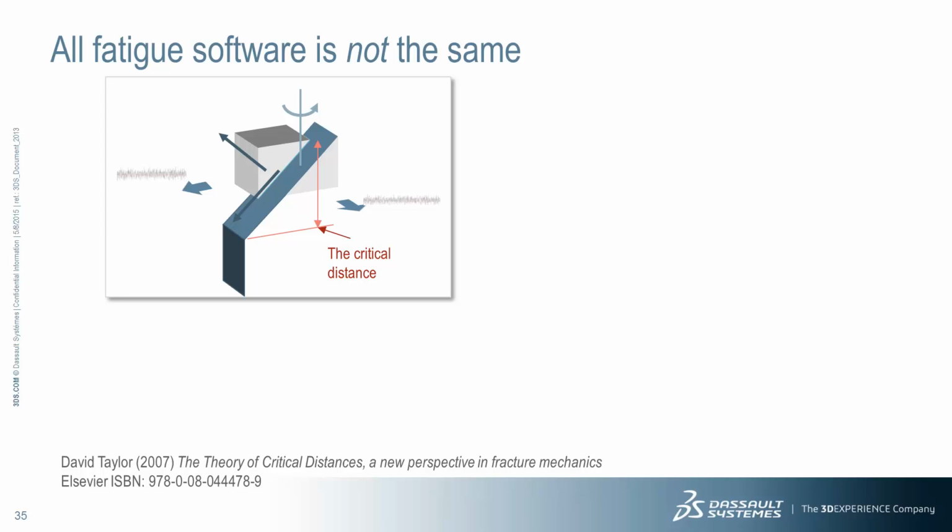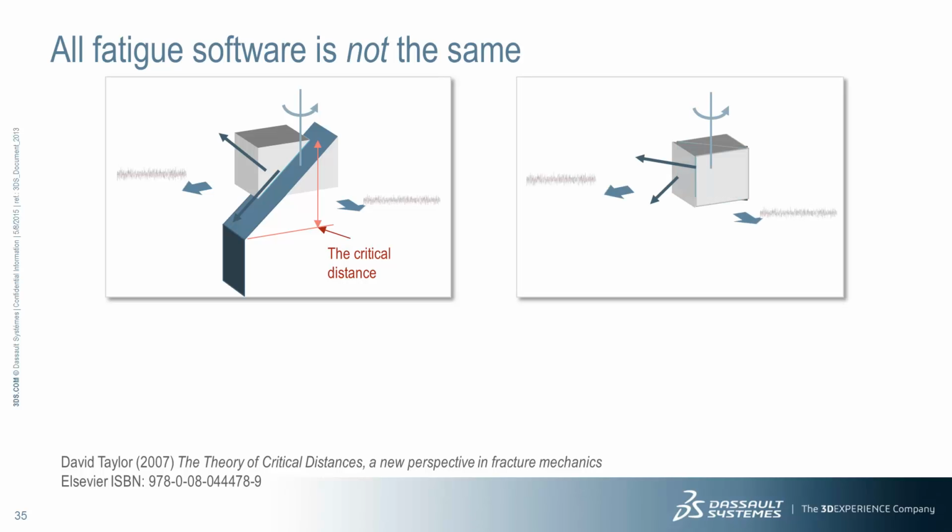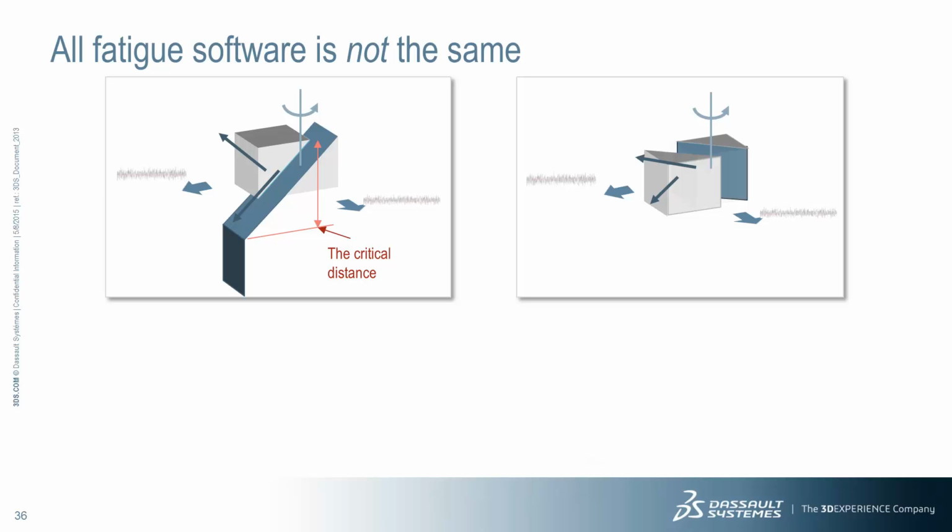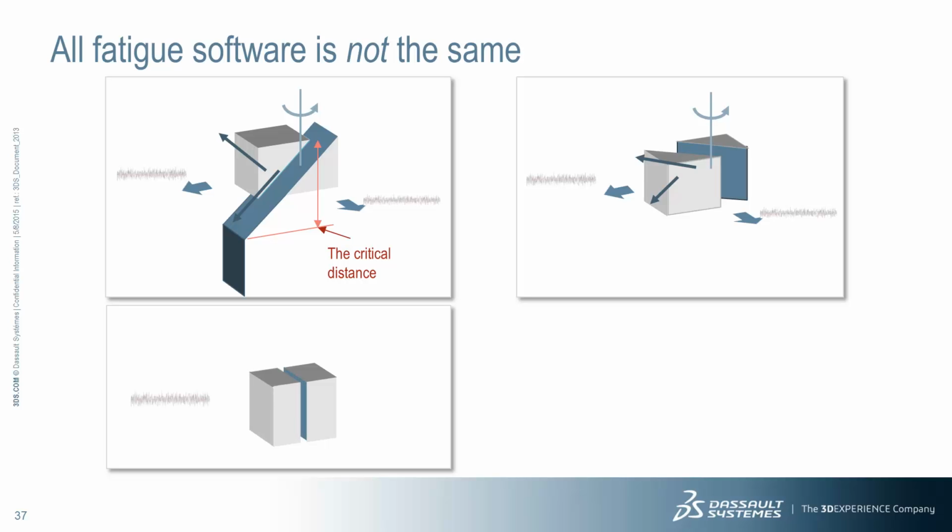Looking at the second cube, for some stress conditions, the crack initiation plane is shown here. Again, the mechanism is a combination of shear and normal strains, and again for complex loading, FESafe will determine if there's a need to search around many orientations of this critical plane. Looking at the third cube, most metals crack on shear planes, but cast metals crack on principal planes. FESafe makes the selection automatically in a model like this. The analysis process is repeated for each node in the model.